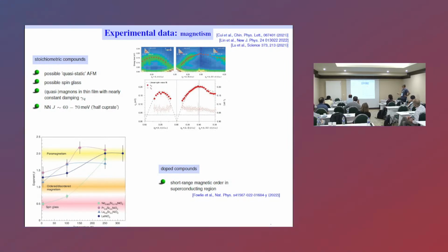A very nice recent study from Jennifer Fowlie, from the Triscone group, and Martin Sauter from PSI and also Stanford. I think this is a very important work. They show that for all compounds, stoichiometric or doped, that we know are superconducting, there's still strong magnetic activity far away from the paramagnetic region in the superconducting regime, meaning that there are still local moments, and importantly on the nickel sublattice. This is not ferromagnetism. They claim really it's coming from the nickel sublattice that has strong, not ordered, but short-range order, spin-glass-like, whatever, but strong magnetic activity even in the superconducting dome.